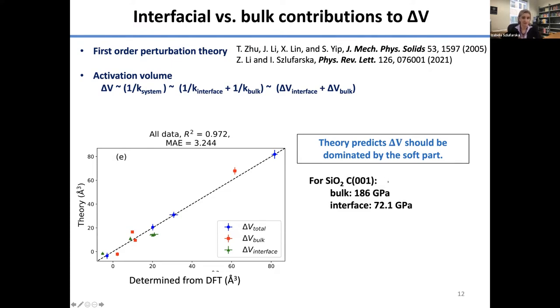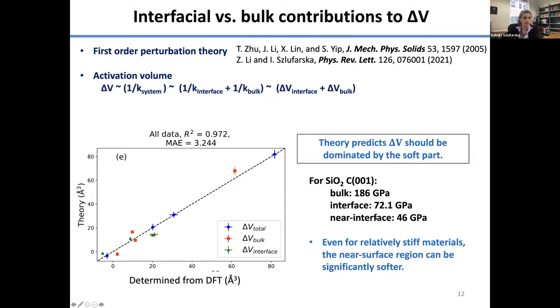And it's actually true of silica as well. If you look at the stiffness or modulus of our system for silica, the bulk is about 190 gigapascal, the interface 72, right? So what's going on? The bulk is stiffer, but it turns out that even for these stiff solids, the near interface region can be much softer because of the surface effect. Near the interface, in the case of silica, a few nanometers, because of the surface effects on the bond orientation and changes in the bond lengths, is actually much softer.